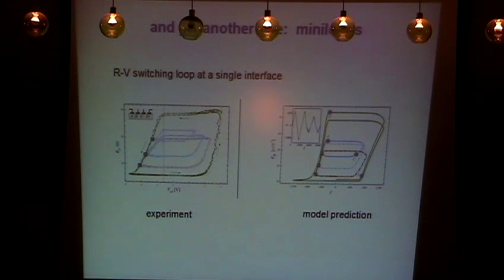Can I ask a question? You were showing numbers. If you look at the thickness dependence of the effect in the two-terminal device, what are the consequences of the thickness of the oxide? It is not much, because everything is happening at the interface. When you get into a thickness comparable to that, I think you get into trouble, at a thickness just below, say, 10 nanometers or something like that. All these Hewlett-Packard experiments, I think they're already working at the level of these interfaces.